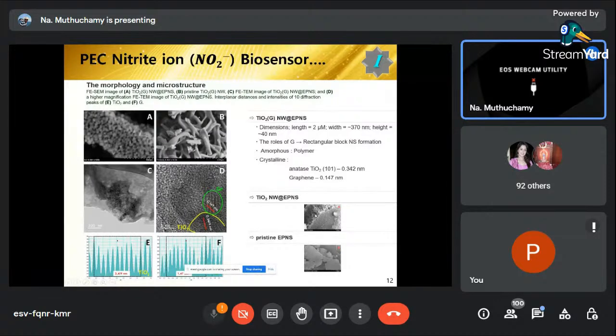You can see that without graphene, the shape of the nanosponge is kind of amorphous and unshaped. It's not a rectangular shape. So that's why graphene plays a main role in shape control. And here you can see the pristine polymer nanosponge only, it didn't show any porosities or any morphology-controlled structures. For that reason, we confirmed that graphene plays a main role in the rectangular, block-like nanosponge formation. Also, the polymers play a role in the amorphous structure, and TiO2 graphene plays a main role in the porous and rectangular shape structure.